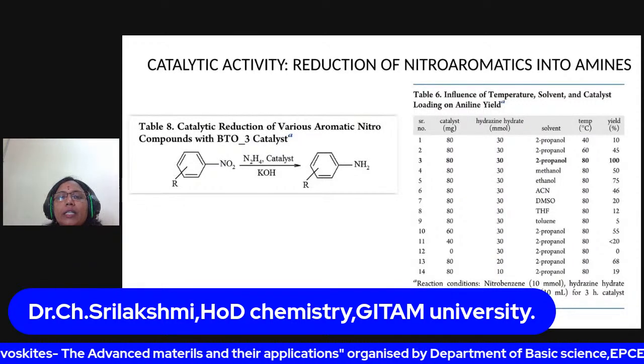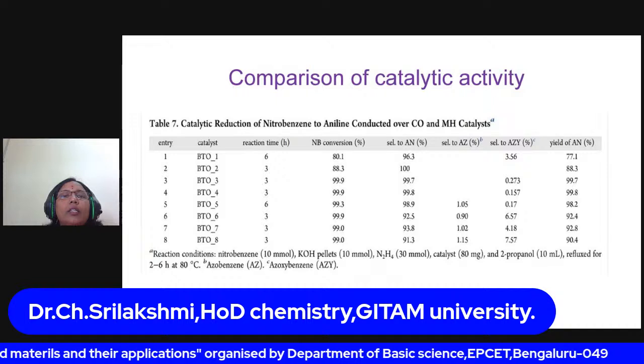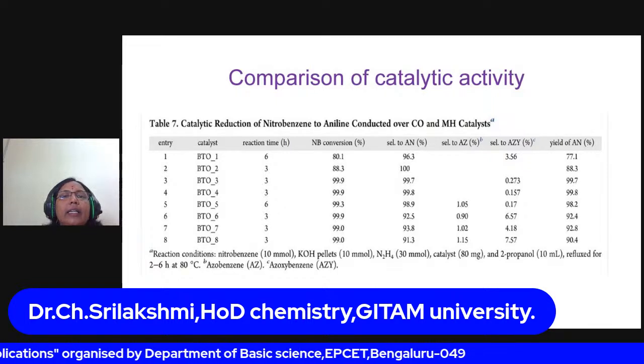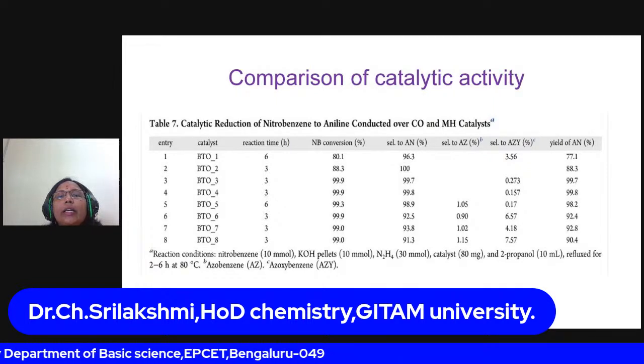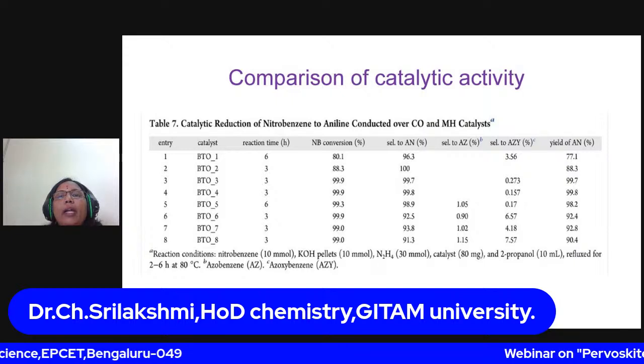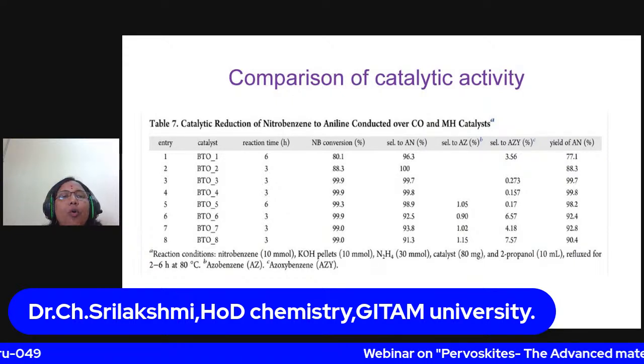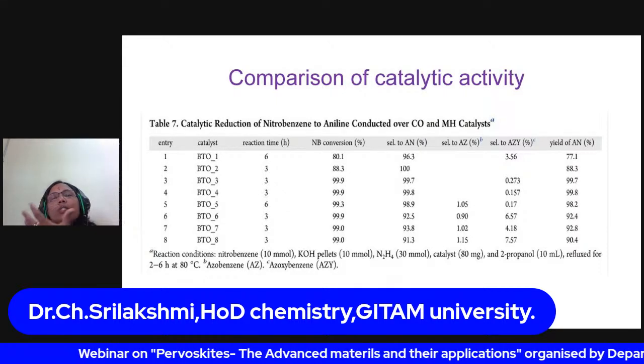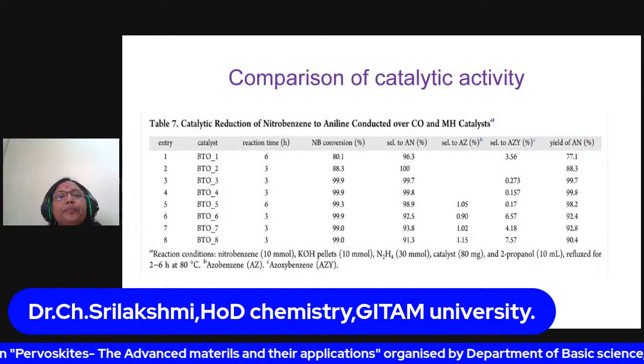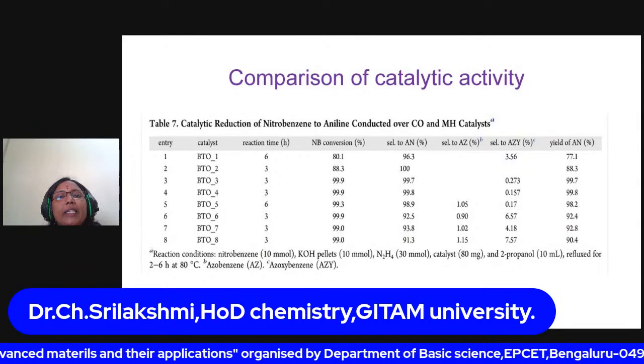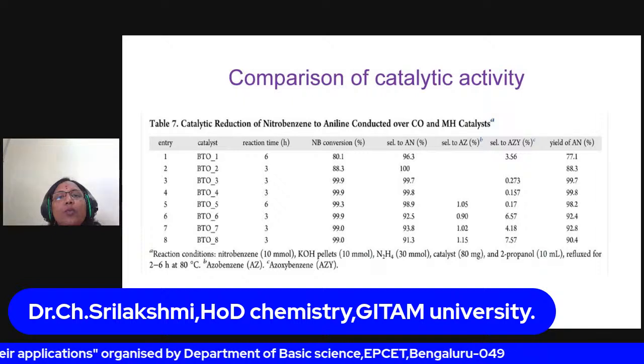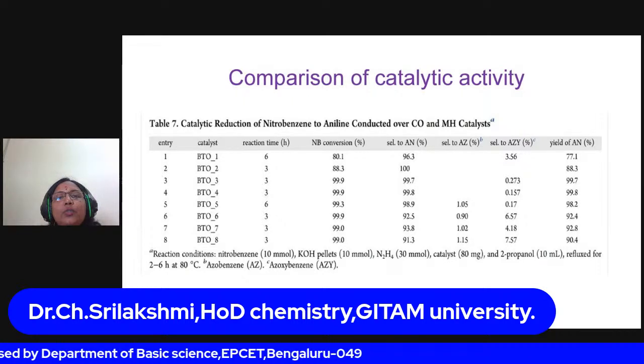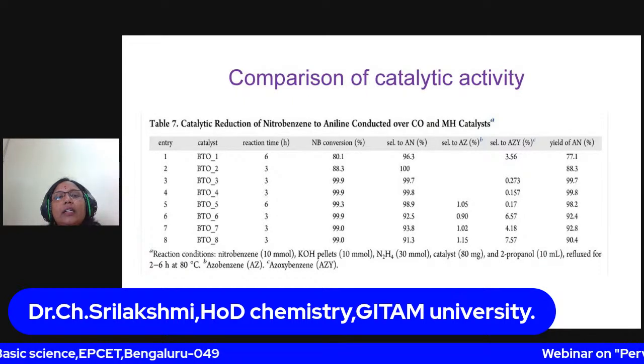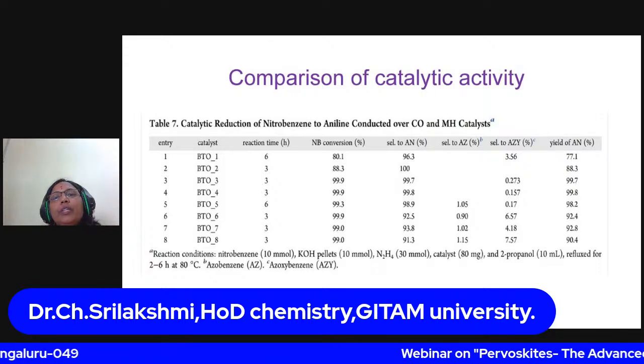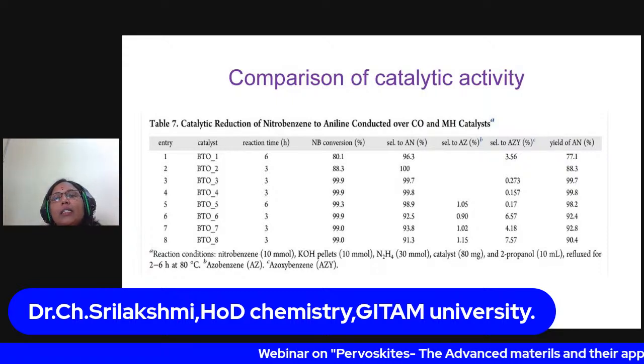So we kept these reaction conditions constant and ran the catalytic reduction over all the catalysts synthesized via CO and microwave. The first four here are CO, meaning conventional oxalate method synthesized catalysts. First, barium titanate required 6 hours and is less active, giving only 80% conversion with 96% selectivity in 6 hours.